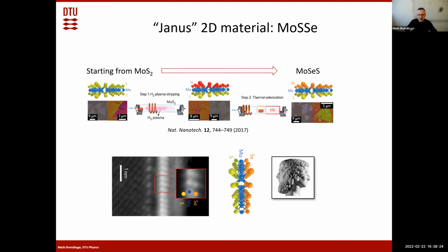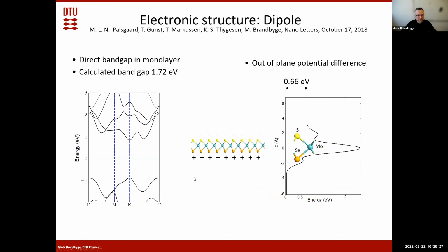The interesting thing about this Janus material is that it's a semiconductor, and it's a direct bandgap semiconductor in this case. But also there's a built-in strong dipole in the layer, because you have a charge transfer from the selenium to the sulfur. So you have a dipole layer, and it's quite strong. It means that there's a potential difference between the two sides of this Janus structure of 0.7 volts.